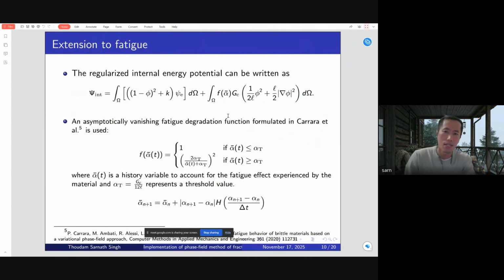We can capture that by incorporating one function, which is the fatigue degradation function. It is given by f of alpha bar, and it is associated with GC. This f of alpha bar is shown here, and here alpha t is an energy threshold. This is obtained from the maximum stress. When this alpha bar is below the threshold, its value is 1, and once it crosses the threshold, then f of alpha bar is represented by this function, and this alpha bar, which is here, is given by this expression.